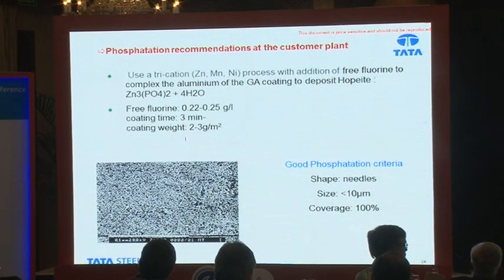So this is a change which we tell the automakers to make: put a little bit of free fluorine in the bath, typically about 0.22 to 0.25 grams per liter, and this takes care of the alumina layer.